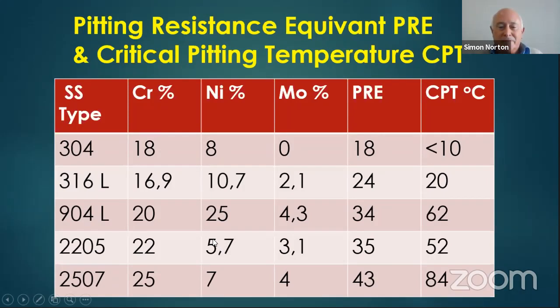with the nickel. The molybdenum is also there, and that's there to serve the purpose of fixing pitting corrosion and preventing it. And then you can look at the PRE numbers, the pitting resistance equivalent number, and then the critical pitting temperature, which you can see for conventional 304 stainless steel is less than 10 degrees centigrade. But for DUPLEX 2205, it's 52.